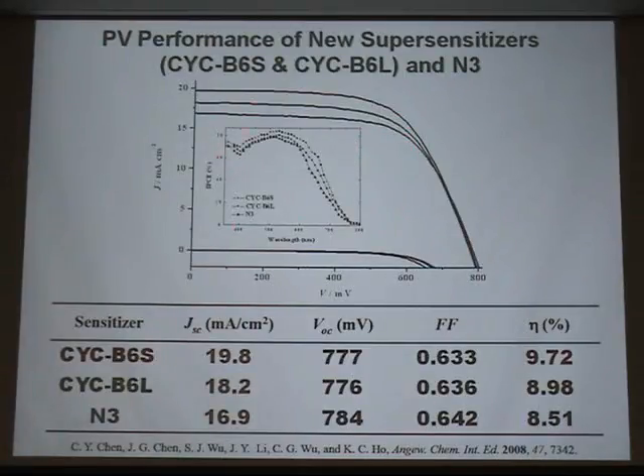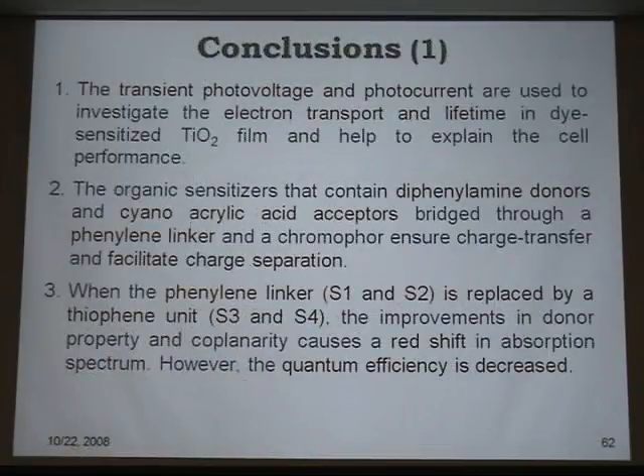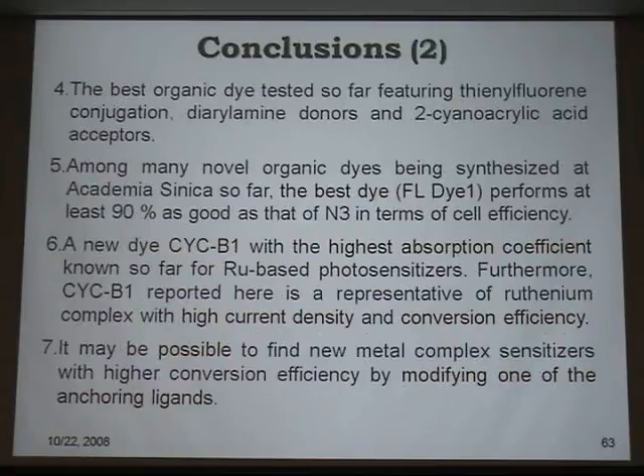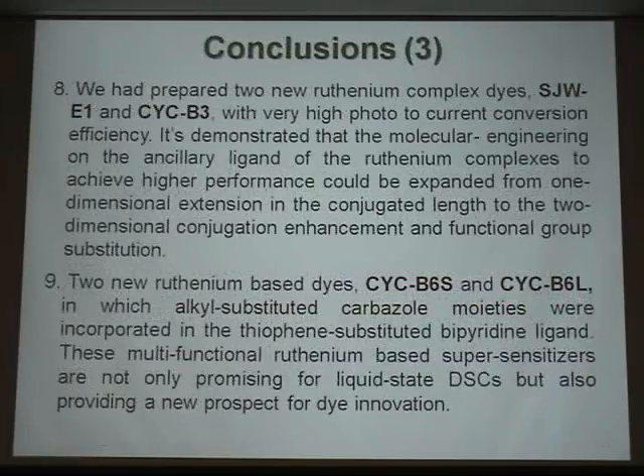And here is N3. So my conclusion is that the transient photovoltaic technique can be a very important tool to judge the performance of DSSC before making a real cell. And also organic dyes such as S1, S2 have a very high efficiency, but the efficiency is not high enough to compete with the existing dye. However, dyes such as Dye-1 we synthesized get 90% of efficiency as compared to N3, which tells us that there's still a lot of room for improvement because organic dyes have the advantage of being cheap. And the CYC system, whether it's CYCB1 or CYCB6, all exceed the efficiency achieved by commercial dye.